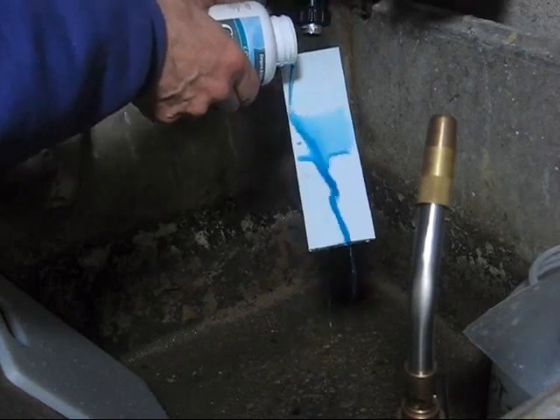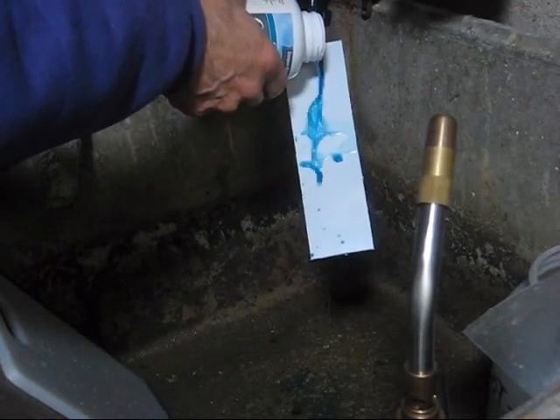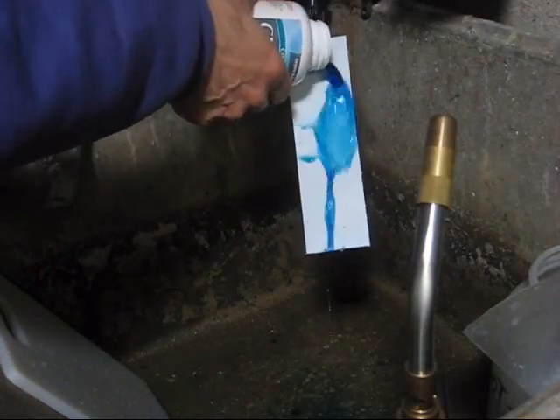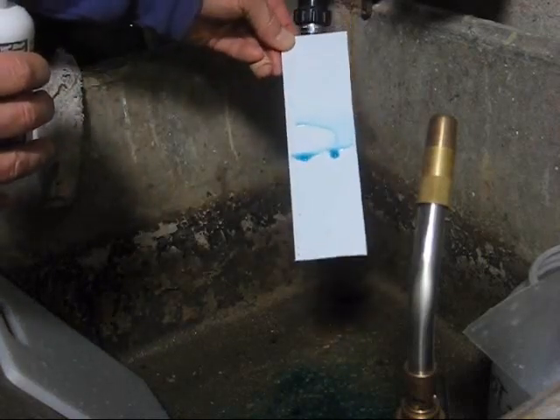There's some colored water - this shows it even a little better. There's a whole band in there where it was heat treated just a couple of seconds with a propane torch where the water very clearly wets the plastic much better than it does anyplace else.